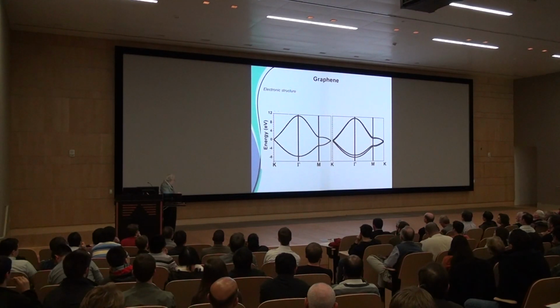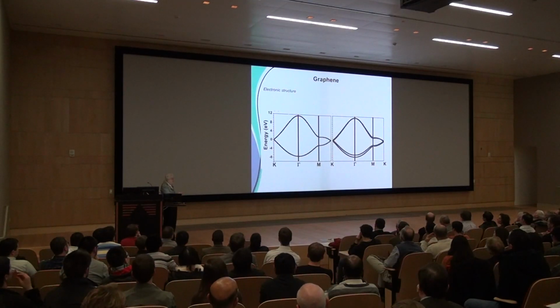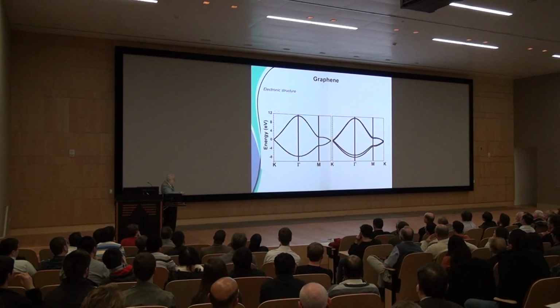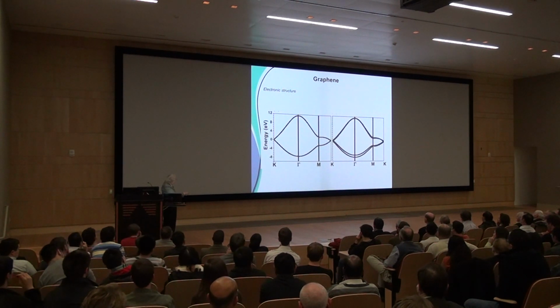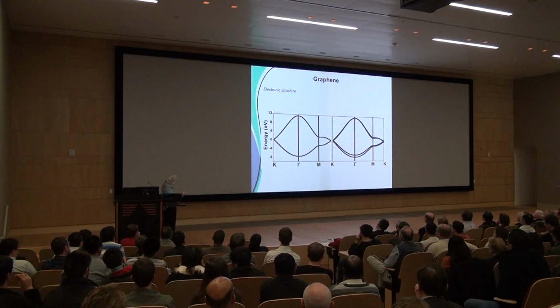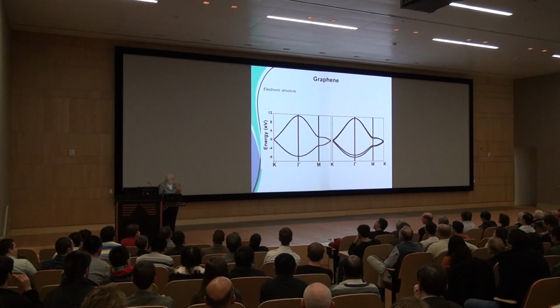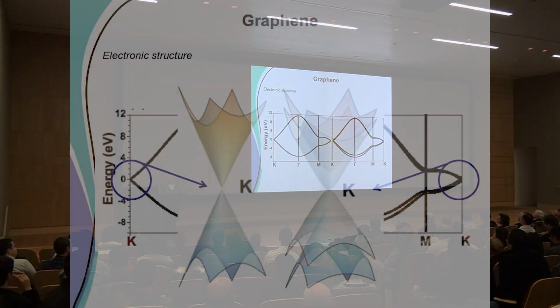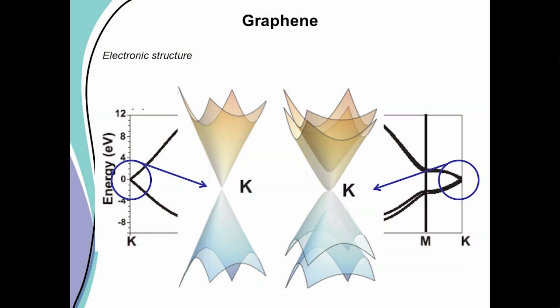So single layer and double layer, I thought I'd show this to you because they're very different, but they're very similar. If you look at the electronic structure over the whole zone, the Brillouin zone, reciprocal space, they look almost the same, right? But if you look at the K point, where the action is, where the Fermi level is, the Fermi level goes through the 0 point. For the single layer, you have a linear E versus K. And for the bilayer, it's quadratic. And that makes the electronic structure properties very, very different. It looks almost the same, but the properties happen to be very, very different.